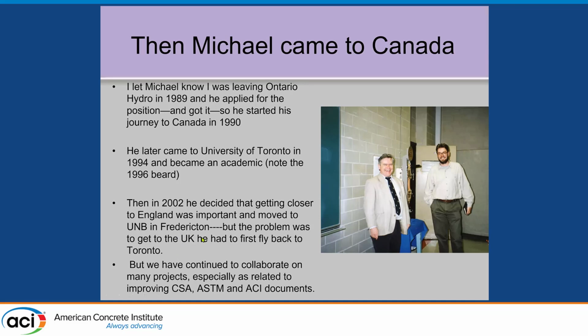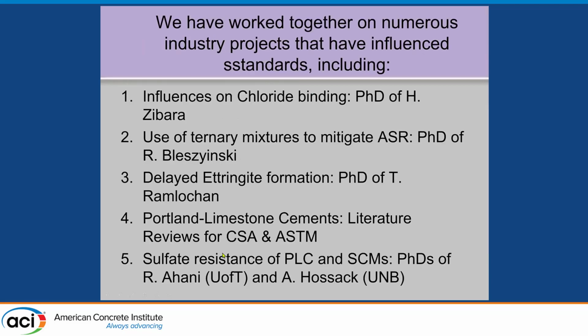But anyway, we've continued to collaborate on many projects we did beforehand and we do now, especially related to standards. We've been involved with a lot of industry projects that have influenced standards, including chloride binding, influence of chloride binding, ternary mixtures to mitigate ASR. We did that for the cement industry in Ontario with the highway department here. Delayed Ettringite formation, I'll talk more about that. And Portland-Limestone cements, working on the background to justify including Portland-Limestone cements in the various standards in Canada and then in the US. We've also had a joint project working on sulfate resistance of Portland-Limestone cement together with SCMs, which resulted in 2 PhDs, and I'll talk more about that.